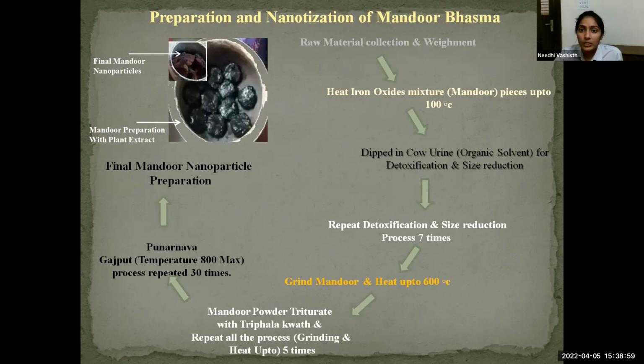Firstly, we take raw materials and heat the iron oxide mixture, that is Mandoor pieces, up to 100 degrees Celsius. Then we dip it in cow urine, that is an organic solvent, for detoxification and size reduction. Then we repeat detoxification and size reduction for the 7th time. Again, we grind and heat up to 600 degrees Celsius. Mandoor powder is triturated with triphala and we repeat all the process, grinding and heating, 5 times.